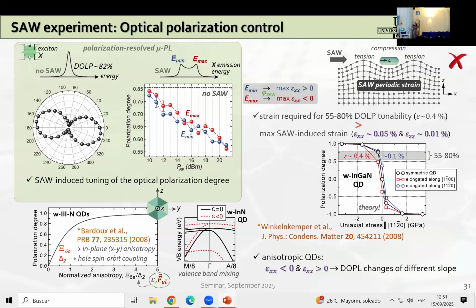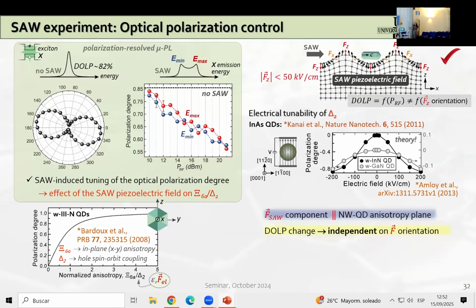So the strain field alone actually cannot be responsible for this reduction of the polarization degree of the emitted photons. And that is because, based on a theoretical calculation here, the actual strain that we would need to obtain such a range of change in the photon polarization degree, well, this one here, is an order of magnitude larger than the maximum value of strain that we can obtain with the acoustic wave. And also for anisotropic quantum dots, such as those that we have in our nanowires, the tensile and compressive strain is expected to produce changes in the polarization degree of opposite slope, which is obviously not what we observe here. So we basically attribute this reduction of the polarization degree to the effect of the acoustic piezoelectric field.